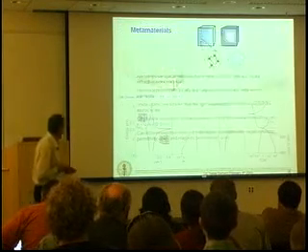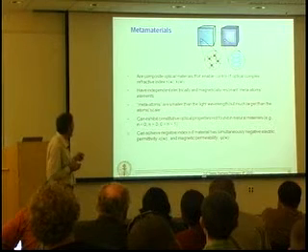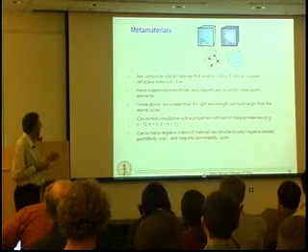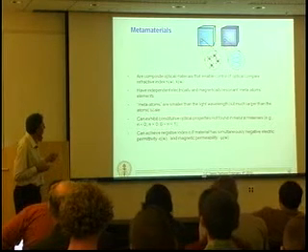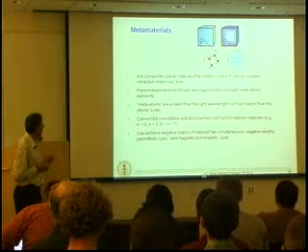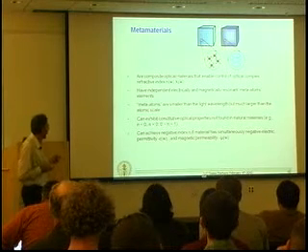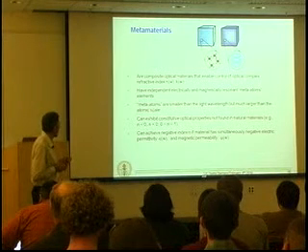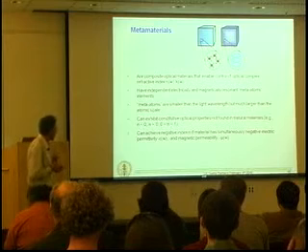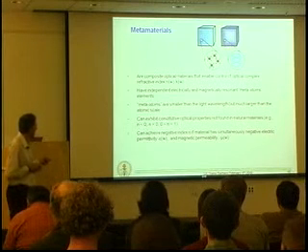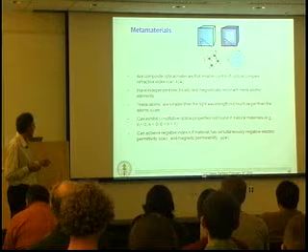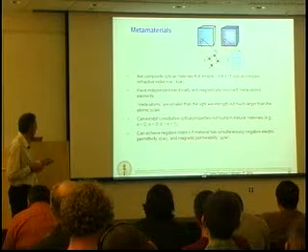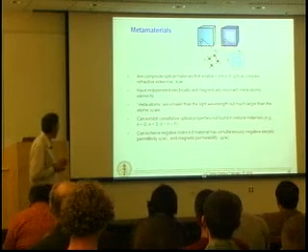Now I just want to say a little bit about looking over the horizon at materials such as metamaterials, which are artificial photonic materials that have the characteristic that we can tune both the electric permittivity and magnetic permeability to change the real and imaginary parts of the complex refractive index. This is a whole separate discussion I'm not going to engage in today, but we can make materials whose composite refractive index can be, for example, less than 1, which has very interesting properties, can be 0.